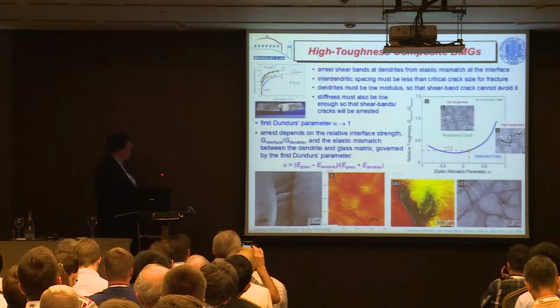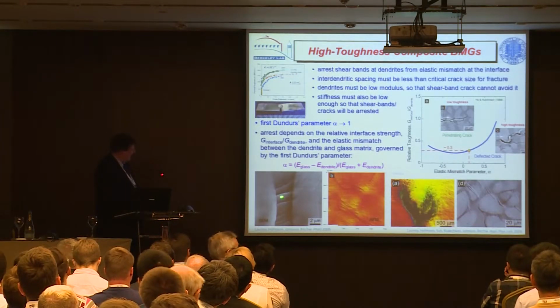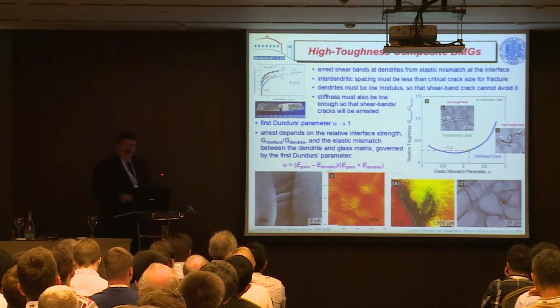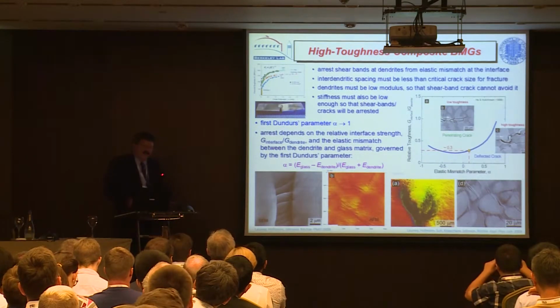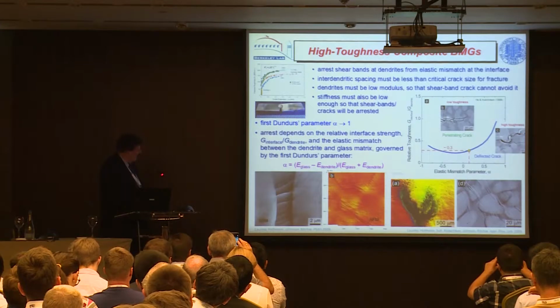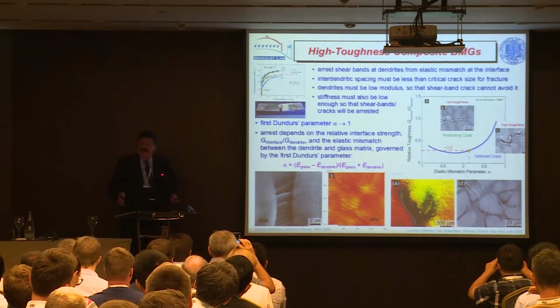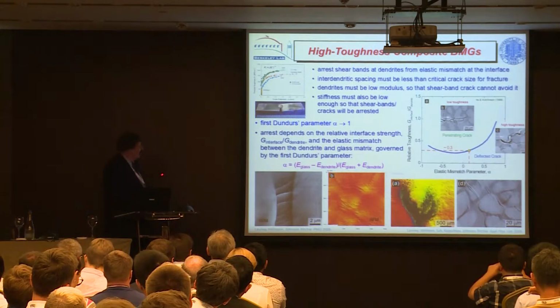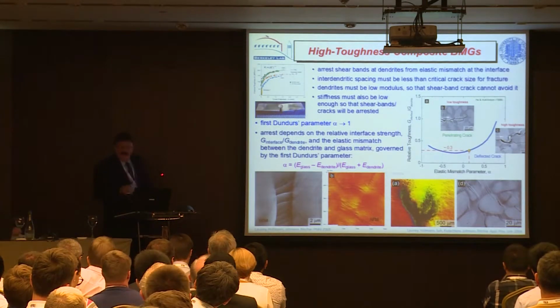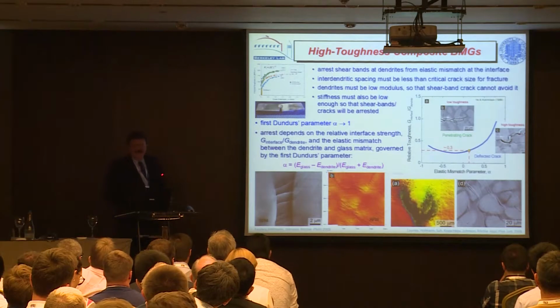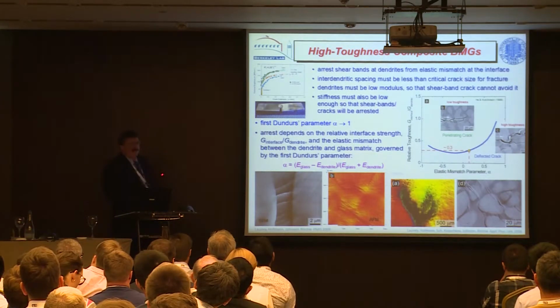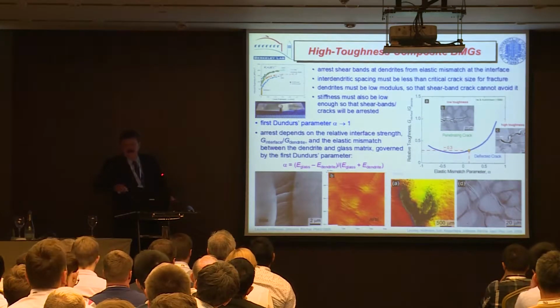There's a couple of things you need to do. You have to have the second phase, as I said, with the spacing small enough so you can't see that size in the monolithic glass. You have to have the shear bands intersecting that second phase, so you need to have a low modulus, because of course cracks will tend to follow a low modulus phase. And then you want them to arrest and not penetrate the second phase.